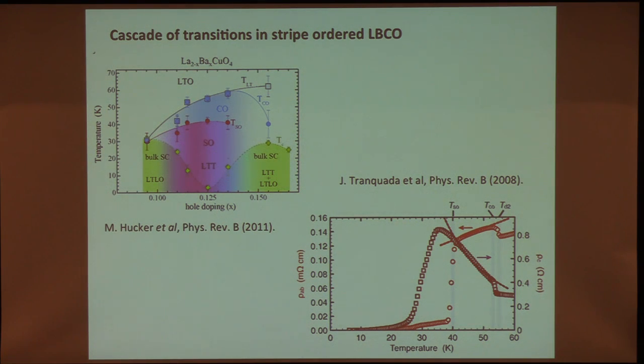Here's the best example of a material that has coexisting density wave and superconducting order in the cuprates. This is lanthanum barium copper oxide. This is a phase diagram as a function of barium concentration. And you can see the complexity that I was talking about. Here's the onset of charge density wave order. There's the onset of spin density wave order. Here's the superconducting TC as a function of doping. They obviously interact with each other in some very complicated way. They all have more or less the same characteristic temperature scale.